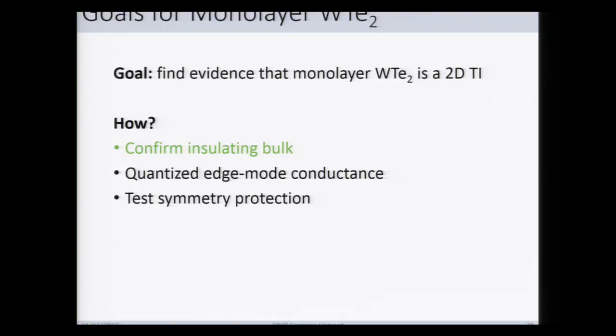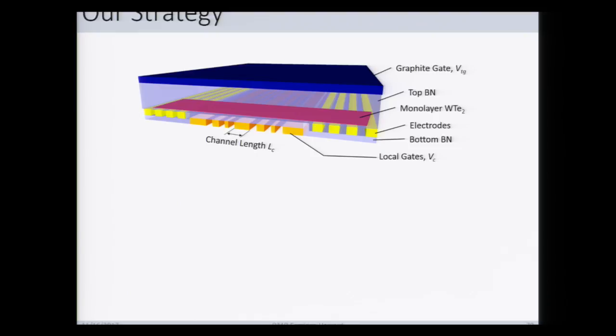So the bulk has been confirmed to be insulating, but what is missing is to see that the edge states that appear to be present can actually be made to approach the quantum of resistance per edge. And then we want to test the requirements of symmetry, time reversal symmetry in particular, once we have this quantized edge conductance. And so the strategy that was employed in our group is to use a device structure like this.